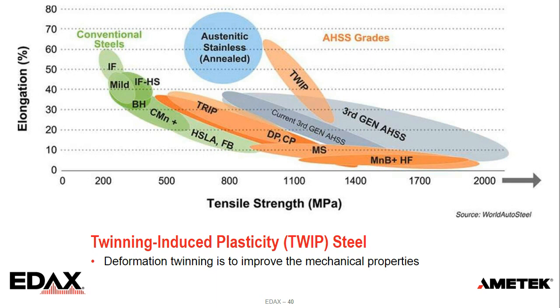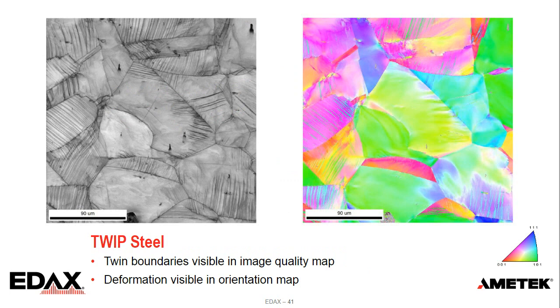For TWIP steels, deformation twinning, and being able to measure and understand that, is what's used to achieve these superior mechanical properties. This is, again, an image quality map of a TWIP steel. You can see the twins come out as those parallel linear features within the microstructure. We can see the orientation map there on the right. You can see the deformation in that orientation map. It's those variations of colors.